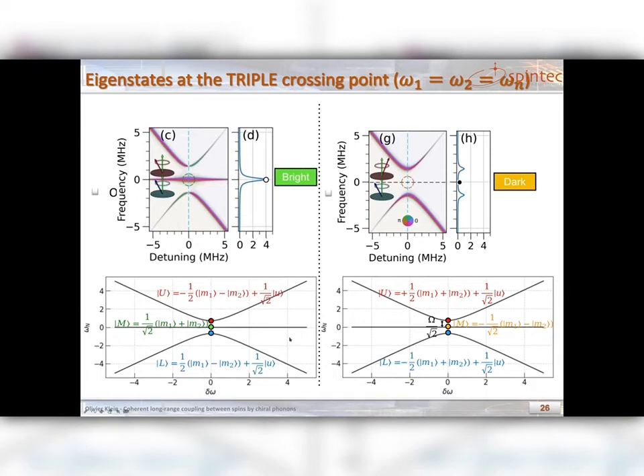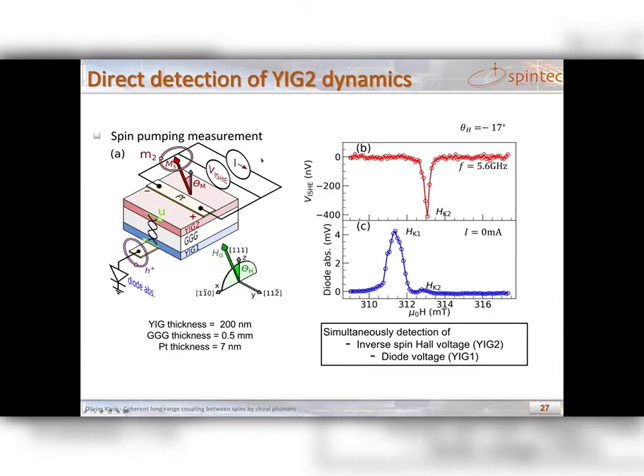And the power spectrum looks like this, and you can calculate that in the case of even mode, you have a dark state, so you have no absorption, while for the odd mode, it becomes a bright state due to the fact that the magnetization rotates in phase. So how do we see this experimentally?